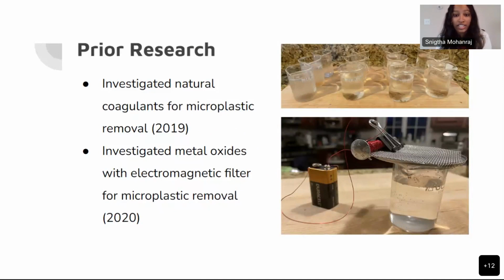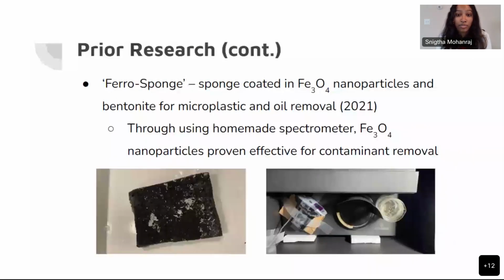In 2021, I expanded this and targeted both microplastics and oil, and I designed the ferrosponge, which is a sponge coated in iron oxide nanoparticles and bentonite to remove both microplastics and oil. And through using the homemade spectrometer that I built, I was able to confirm that iron oxide nanoparticles are indeed very effective for contaminant removal, and this motivated me to utilize them in this current research as well.